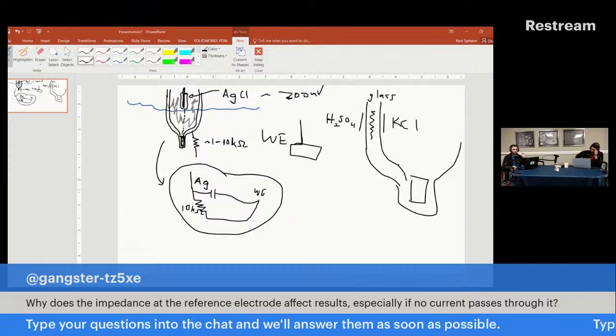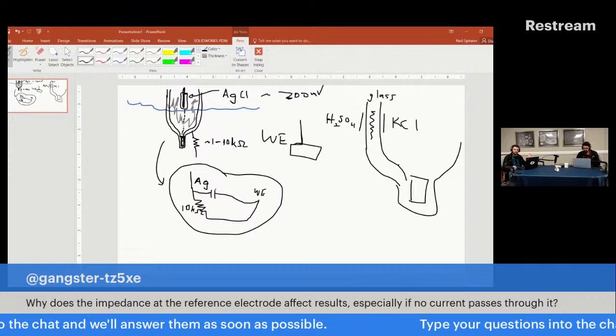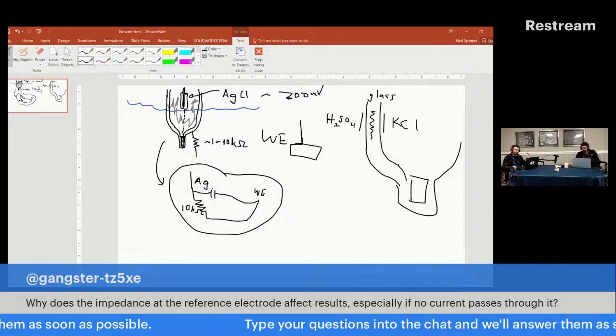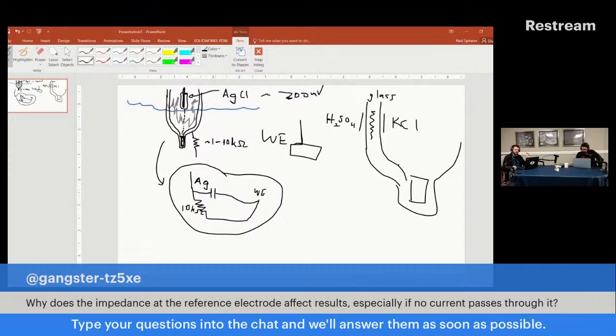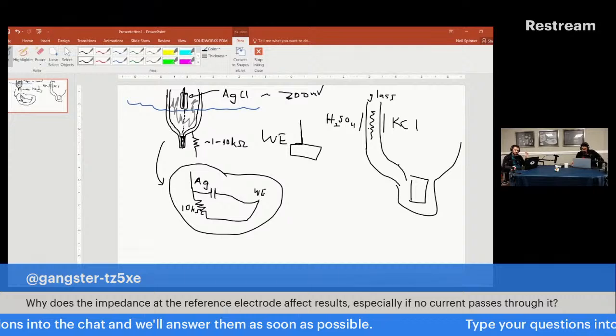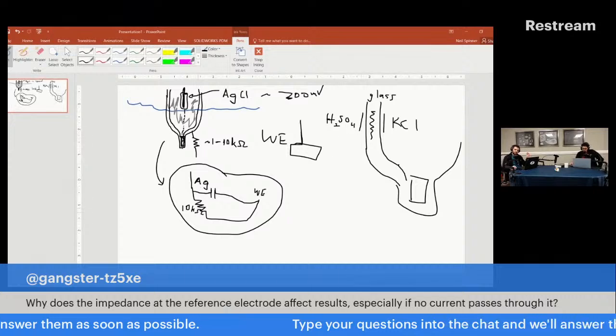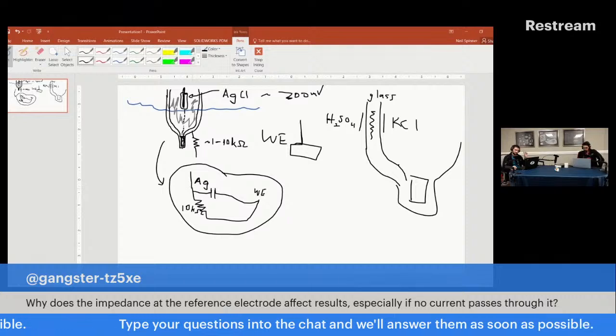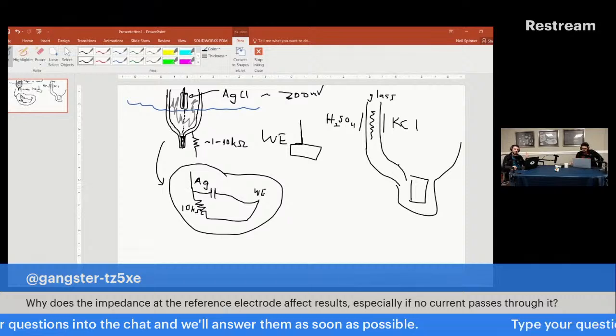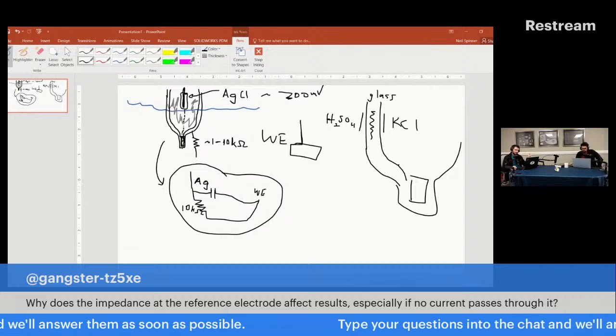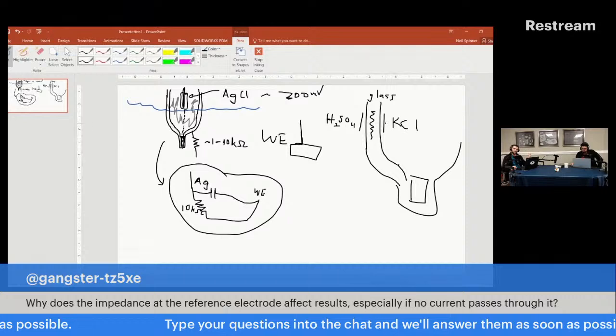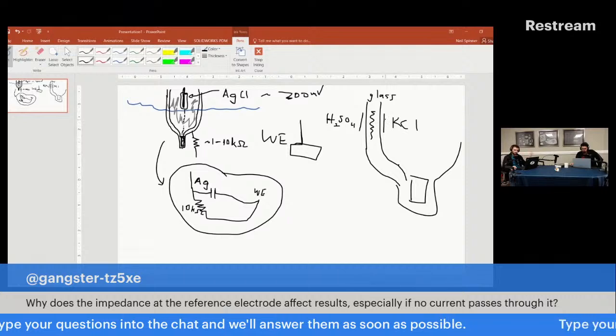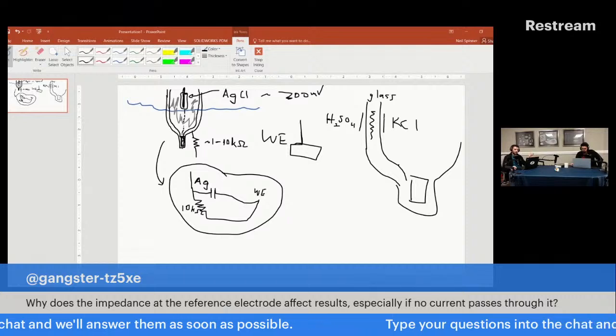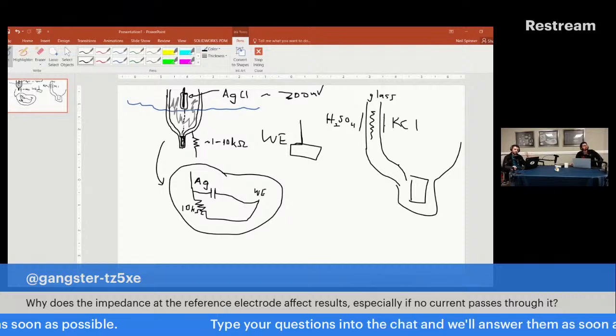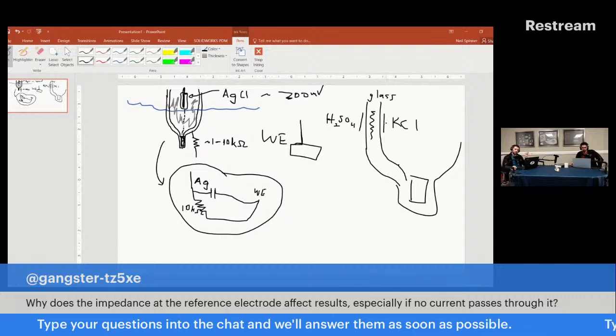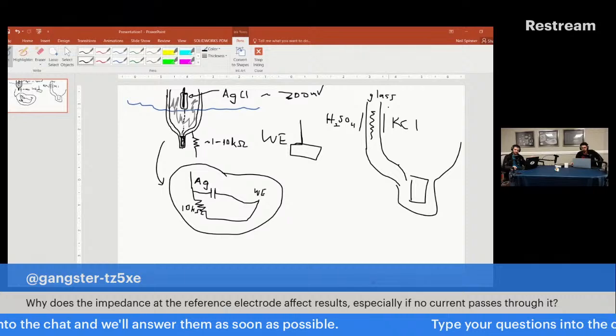It's inversely related. What that means is that at high frequencies, the impedance associated with the capacitance through the glass directly can be lower than the impedance of the frit, which means the potentiostat is going to pay attention to this instead. At high frequency, the potentiostat is trying to communicate directly through the glass wall of the reference electrode. That can't really be done, right? So you get odd results. You basically have no real communication between reference electrode and working electrode at those frequencies in that situation.